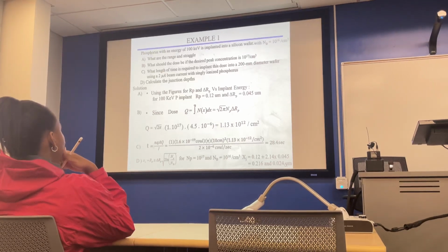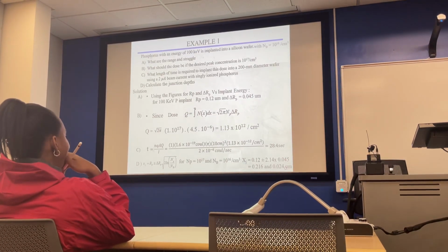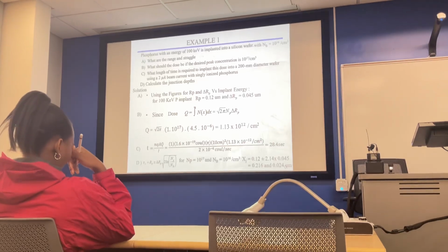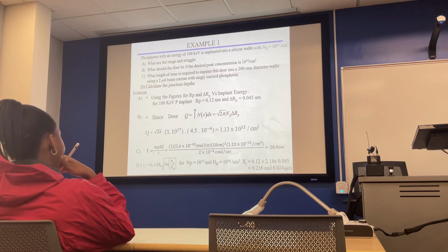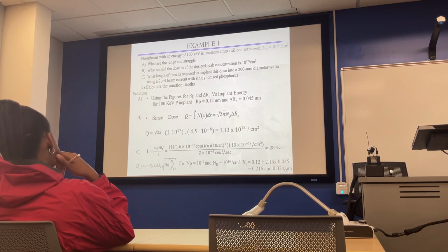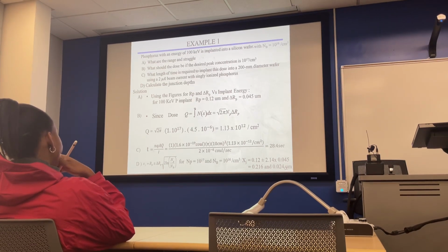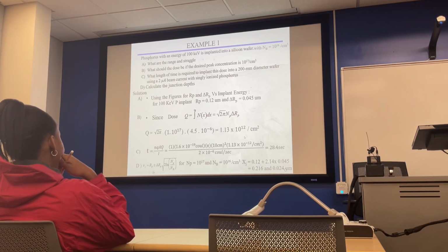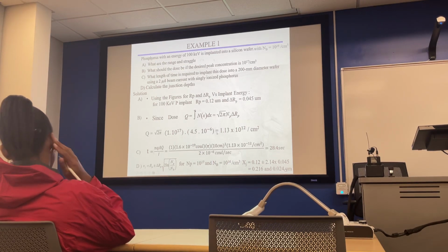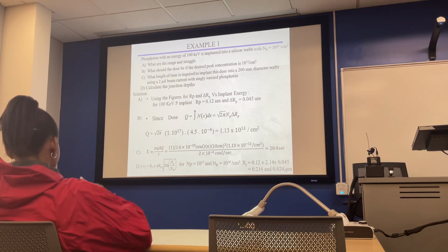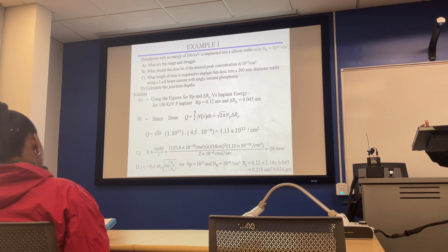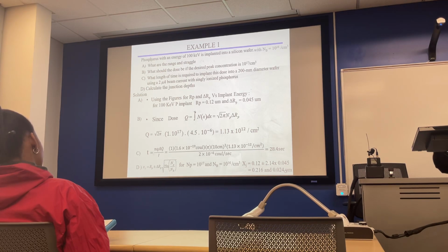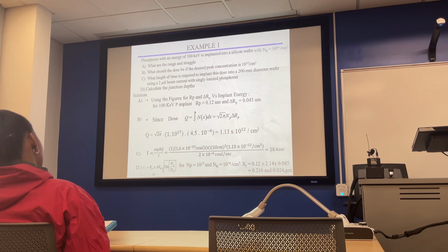Okay. Now, this dose is very hard to even get if you do the regular pre-deposition diffusion, because those numbers are very high very quickly, because your surface concentrations are so high when you do the normal tube diffusion. And this was one of the advantages we talked about, that the beauty of ion implantation is that I have a very wide range of doses, and you can see that I can tailor my dose just by these two numbers, right?